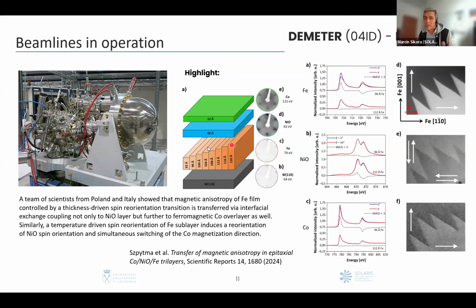So the example here is films of iron of very different thickness, which were covered with an antiferromagnet, nickel oxide in this case, and again with some ferromagnetic layer, in this case it was cobalt. And then it is known that depending on the thickness of iron on tungsten, the easy magnetization axis is in plane or out of plane. And the question for this study was whether the cobalt on top will also follow the anisotropy of this film down here. And that was really confirmed that indeed when the iron has switched the polarization, also the cobalt film on the top. So this is kind of an example for spintronic application.